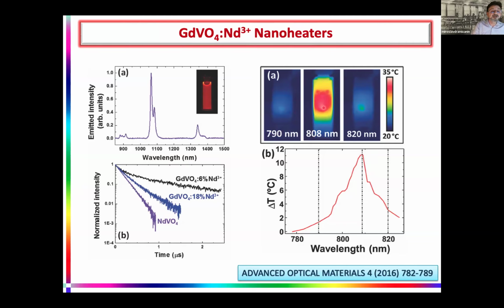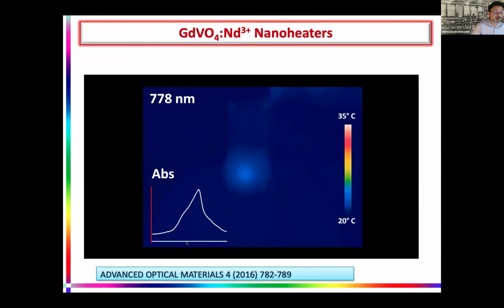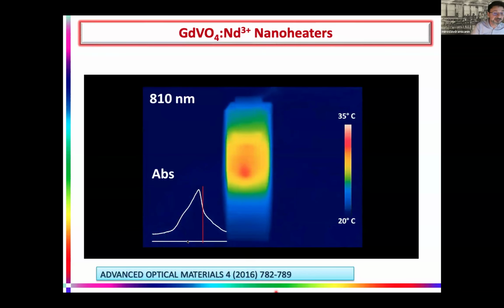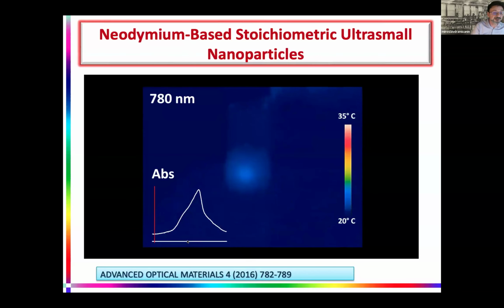You can clearly see the increase in temperature. This is measured by a thermovision infrared camera. So you can clearly see that the heat is generated inside the cuvette with the nanoparticles. And here is an example of thermal imaging of the cuvette while we are scanning a tunable laser through the absorption peak of these nanoparticles. And you can clearly see how this heat is rapidly generated.